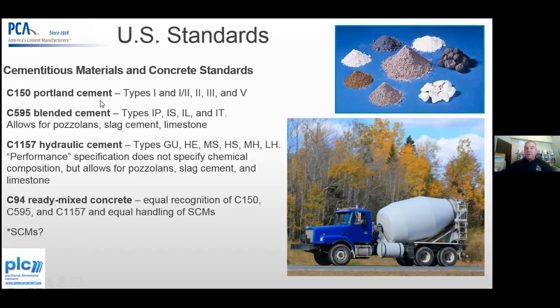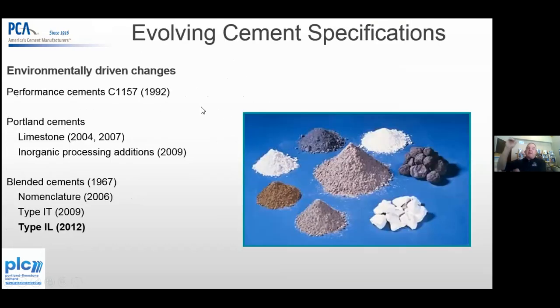C150 has undergone quite a number of changes over the past 20 years, 15 years. So in 1992, 1157 came out with their first attempt to come up with something that was more environmentally friendly. And it still hasn't gained traction. Portland cement has made some changes in the C150 realm. In 2004, we were able to add up to 5% limestone addition. In 2007 and 2009, some changes for inorganic processing additions were recognized, where you can use a slag, a fly ash,